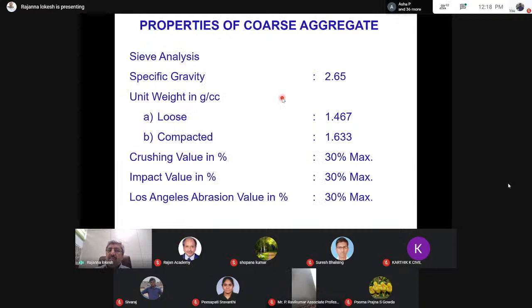Generally, the specific gravity of coarse aggregate will be around 2.65. Then loose density will be 1.46 gram per cc, and compacted 1.63 gram per cc. The crushing value of 30%, impact of 30%, loss angeles abrasion of 30%. These are the maximum limits.